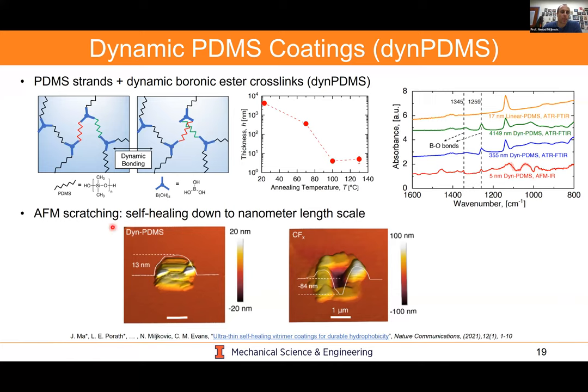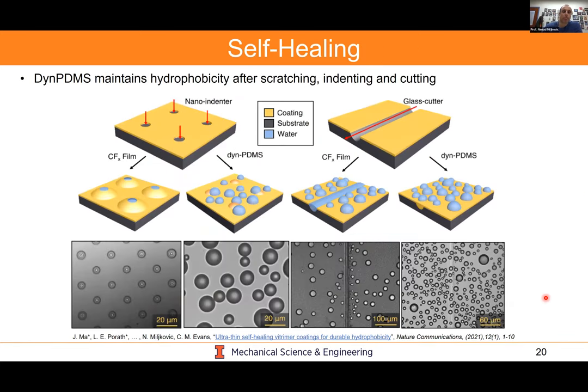What you'll actually see is that what we call here dyn-PDMS, dynamic PDMS, after you scratch it, it'll dynamically self-heal. Whereas if you were to take a conventional chemistry like CFX, this is a non-self-healing polymer, this is what the scratch looks like after you're done with it. So there's no self-healing, there's no flow. The defect is actually left inside the coating. So this was first proof to us that this actually works and could have good potential for dropwise condensation.